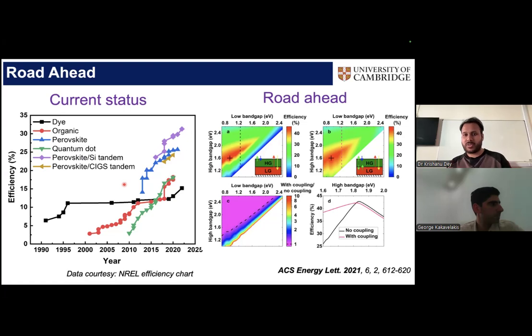So if you want to stack 2 different perovskites with a higher band gap and a lower band gap, and you want to get the highest efficiencies, this is a paper that shows what maximum efficiency you can reach if you choose the right combination of band gaps. And you can see that basically the lower band gap perovskite needs to have a band gap of about 1.2 electron volt or close to that. And unfortunately, the traditional lead-based perovskites cannot reach that band gap,